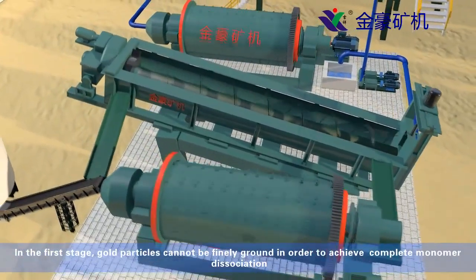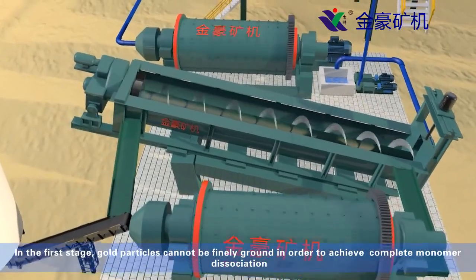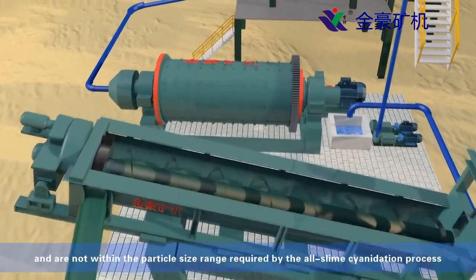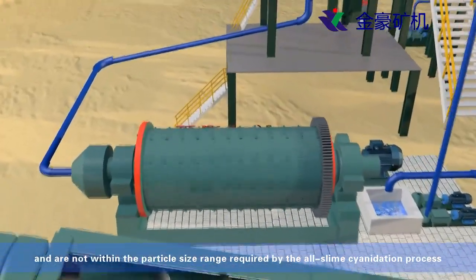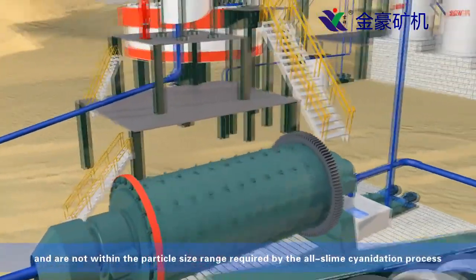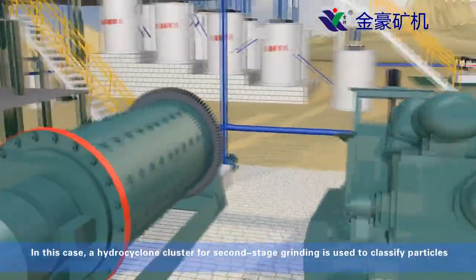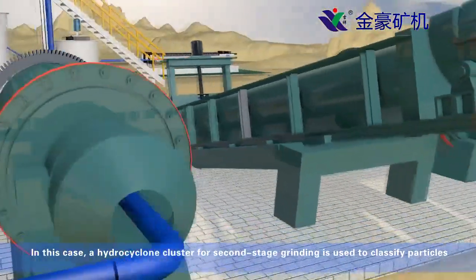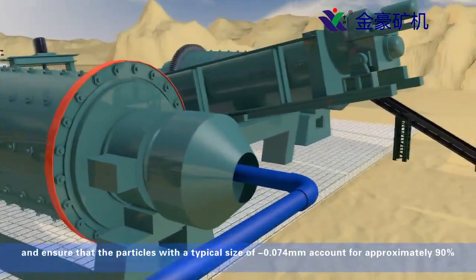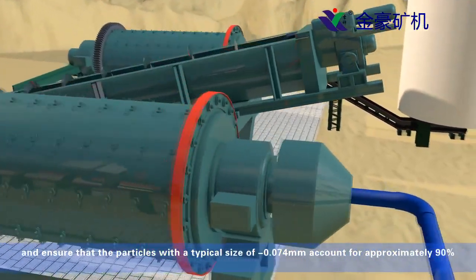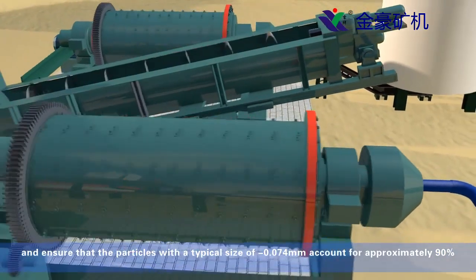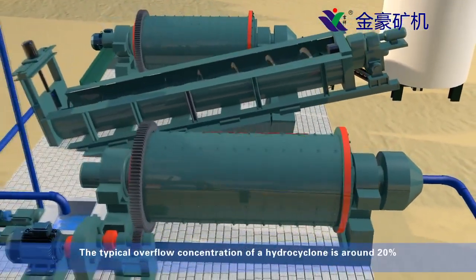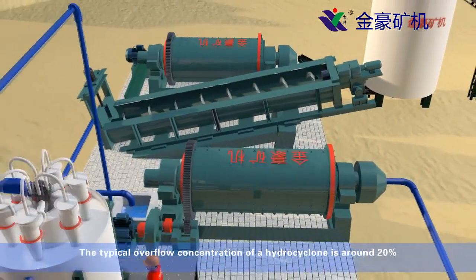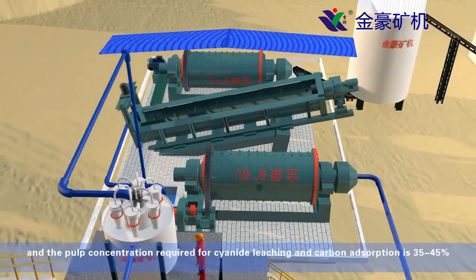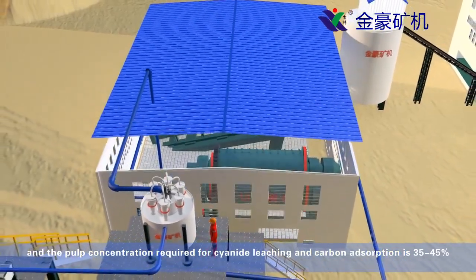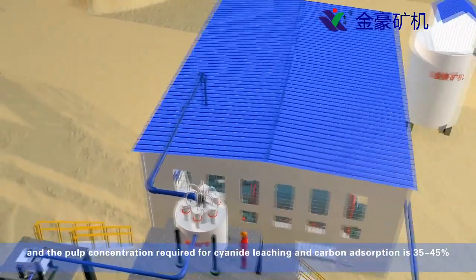In the first stage, gold particles cannot be finely ground enough to achieve complete monomer dissociation and are not within the particle size range required by the all-slime cyanidation process. In this case, a hydrocyclone cluster for second-stage grinding is used to classify particles and ensure that the particles with a typical size of negative 0.074 millimeter account for approximately 90%. The typical overflow concentration of the hydrocyclone is around 20%, and the pulp concentration required for cyanide leaching and carbon absorption is 35 to 45%.